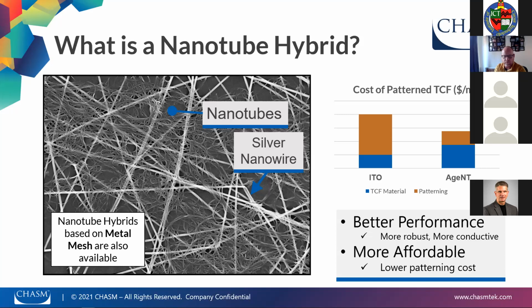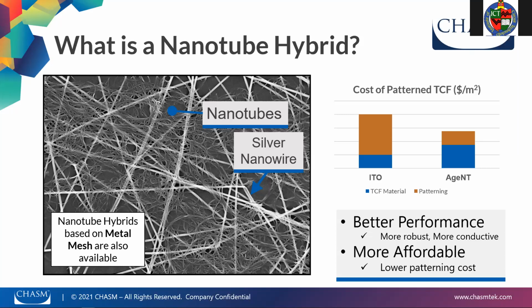There are some truly remarkable properties of nanotubes. Nanotubes are conductive, they're self-assembling, they're environmentally neutral. So when used in a nanotube hybrid, they make the open areas that are traditionally non-conductive in these films conductive. They also bind the wires together to prevent separation or breaking during bending. So you can support applications such as bending or thermoforming, flexible screens, for example, in cell phones. Even if the conductive rods were to break, the conductive redundancy of the nanotubes means that the signal can still be transmitted.